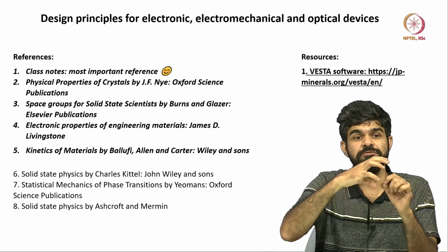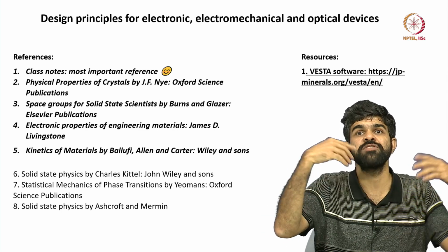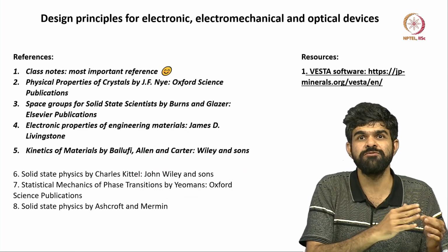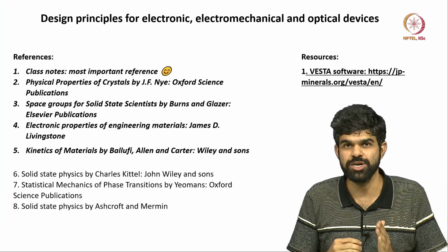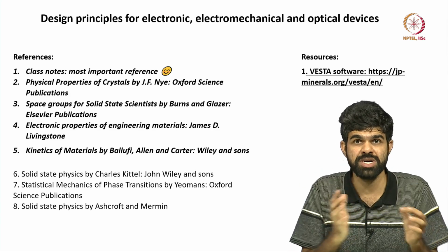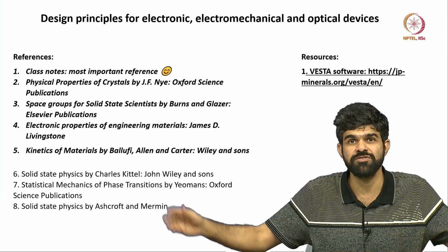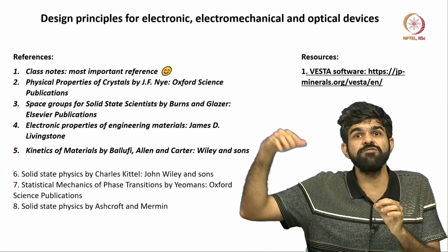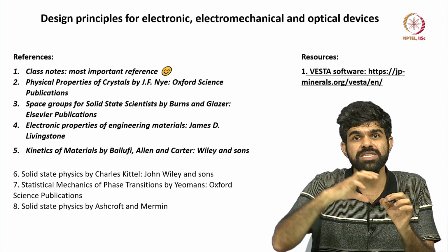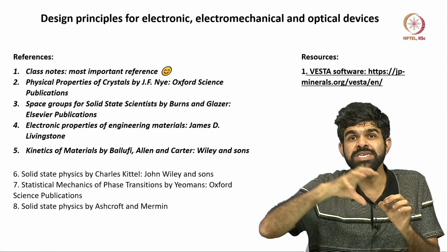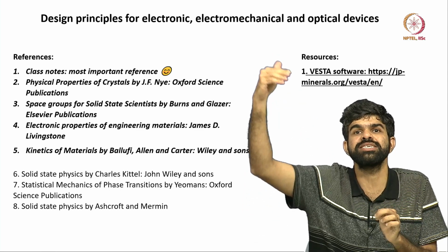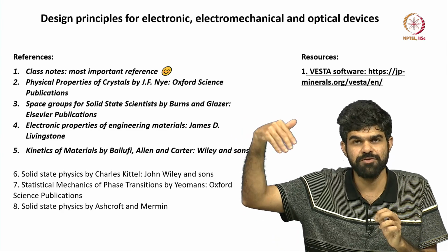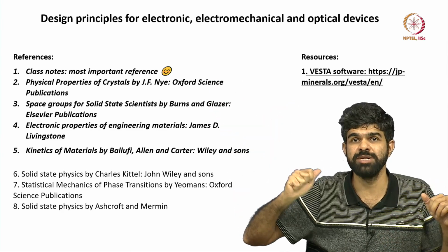Now if my qubit is interacting with phonon, it will forget that it is a qubit, right. So by the time I measure this qubit, it would have forgotten the information that I fed into it initially. So I cannot do any quantum computation if the qubit is interacting with phonon and decohering by itself, right. So I have to get rid of these phonon frequencies where the qubit is interacting, meaning it gives its energy to a phonon, and the phonon has a real state where it can get excited to, right. So I understand what that real state is through some sort of Raman spectroscopy.